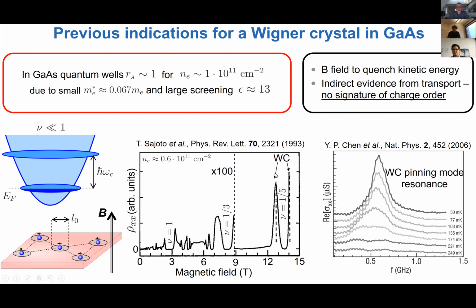And indeed, there have been indications, no proofs, no signature of charge order emerging in the system. But for example, in this relatively old data, one sees that right around the fractional quantum Hall state of 1/5, there are regions with high resistivity, and this resistance can actually be unpinned, can be removed by applying AC modulation. So the idea here is that the Wigner crystal, because of the inevitable disorder, is pinned, and therefore